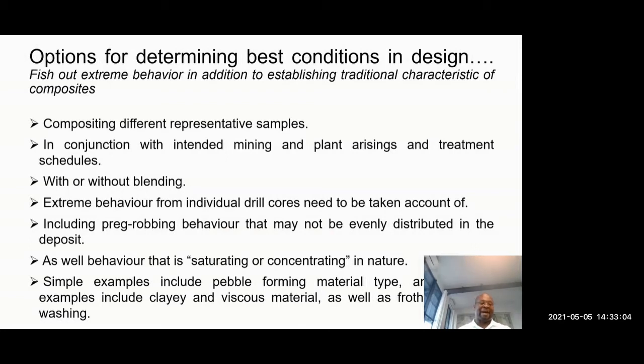Some of that is easy ones, like material that has the propensity to become pebble forming material, which is in the milling circuit that we already know keeps in. It's a pebble for a reason, so it keeps in. But typically that material may not be evenly spread throughout, so depending on how you bring your material through the plant, you need to take a look after that properly. But there are other hidden ones like clayey or viscous material, as well as froth, the ones that need froth washing. Your composition of the material that you tested may not show it, as you saw in the 3 different colors and so on.